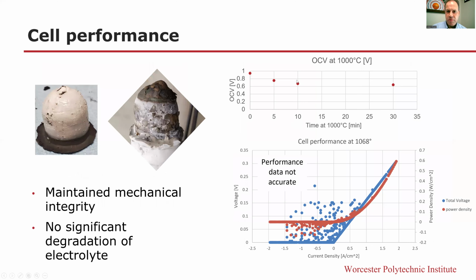So just looking at the performance, we have open circuit voltage up close to the 1 volt theoretical voltage of the CO2 formation reaction. This is at 1 atmosphere, though really in order to run continuously, we would have to run at high efficiency to avoid generating a lot of carbon monoxide. We'd have to run at somewhat higher pressure than this. So we'd want to put the ceramic in compression there.